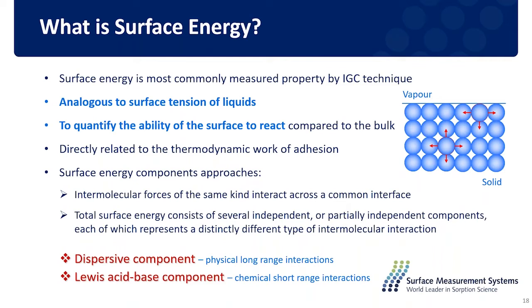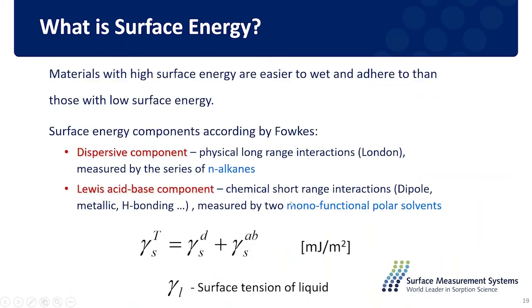hydrogen bonding, dipole-dipole interactions. And to get those different interactions, we need to use a series of nonpolar probes, some alkanes like hexane, heptane up to nonane, and decane, to get the dispersive surface energy. And we also need to use two monofunctional polar solvents, which are widely used such as dichloromethane, ethyl acetate, toluene, and chloroform, to get the specific surface energy of the material. So when we add up the two different components, then we will get the total surface energy of the material.